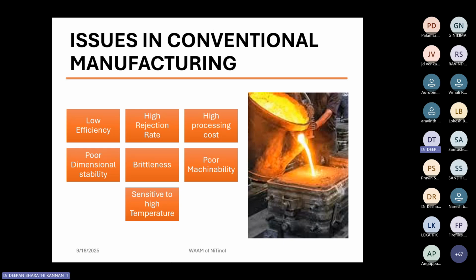For example, if you are taking the nitinol to higher temperature, there may be negative impact on the chemical composition, and it will alter the phase transformation temperature, which in turn affects the shape memory effect and superelasticity. So the process by which we are fabricating the implant or any other actuation system should be carefully chosen so that there are fewer changes with respect to the chemical composition.